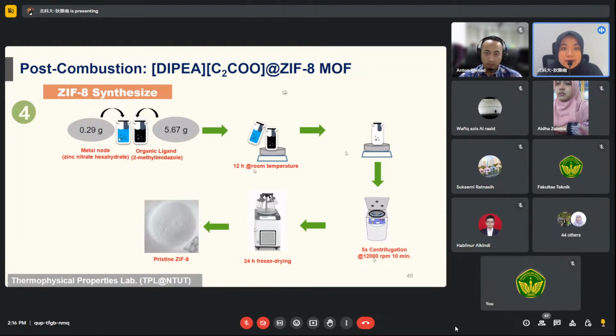And after this, we use freeze drying. Why don't we use the oven? The oven is not good for metal organic frameworks because it can reduce the capability of the absorption process. That's why we use freeze drying. It's much recommended. It's okay to use the oven, but the absorption capability will be affected. Some journals mention the oven; maybe at that time they wanted to compare, or tried some method with high heat to see how the capability changes. But we tried previously and checked that freeze drying is the best suggestion to remove the water content from the ZIF.